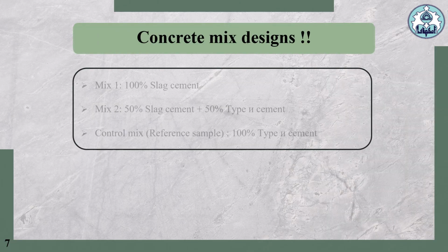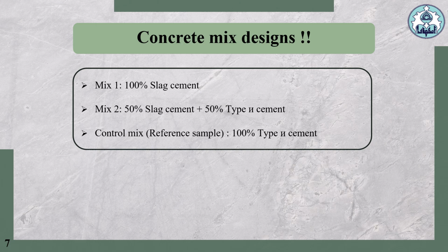In this study, 3 concrete mix designs were prepared. Mix 1 contains 100% slag cement. Mix 2 contains 50% slag cement and 50% Type 2 cement. The control mix, or reference sample, is made entirely of Type 2 cement.